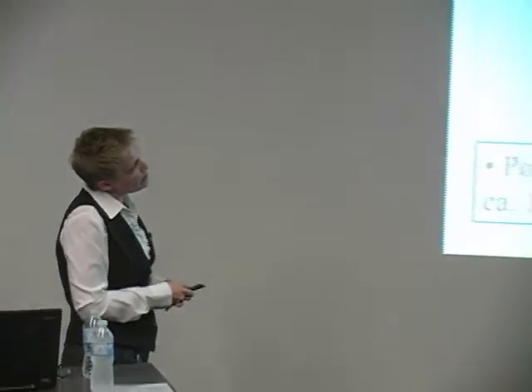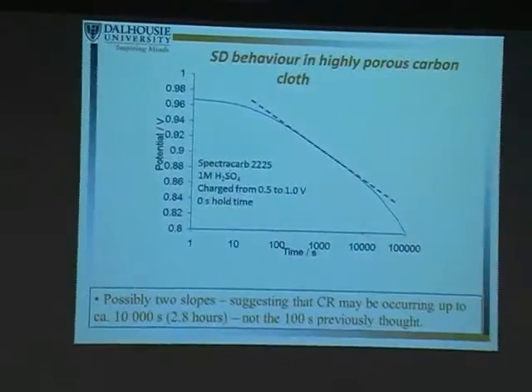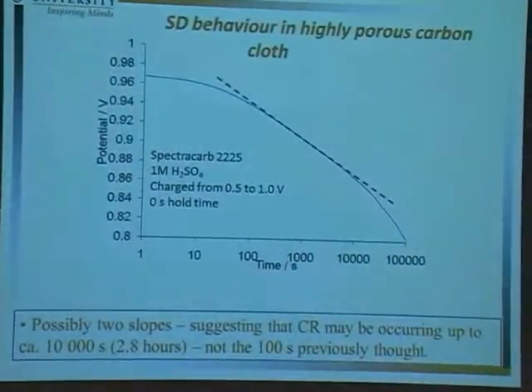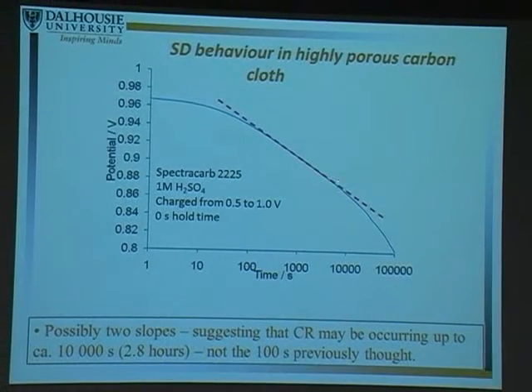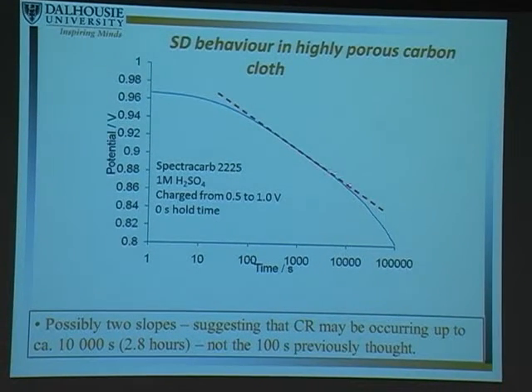So then we go back to our carbon, and we look for very, very long self-discharge times to see if we see something similar. And it turned out that we did. We see a plateau, which we expect for both models. We then see sort of a linear region here, and then we see consistently a change in slope, where the slope is increased. And this is suggesting to us that charge redistribution is occurring and activation-controlled self-discharge is occurring throughout this whole region. And then the charge redistribution stops or becomes minimal. Activation control takes over, and we see this decrease.